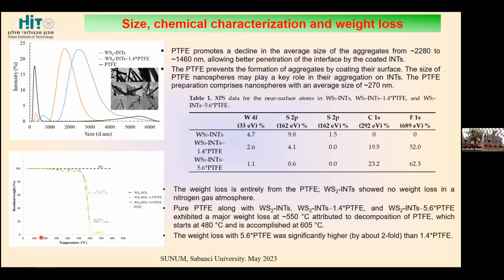Sorry, not resistivity, the friction coefficient, and also their stability at high temperatures, because in friction you generally achieve very high temperatures. The temperature stability was quite high until about 500 degrees. Only then was there some decomposition. The content of the nanoparticles proved to be very pure, and there was just some Teflon outside, mostly in measurable quantities. And as I just said, no weight loss was observed in nitrogen gas atmosphere, so stability was proved.